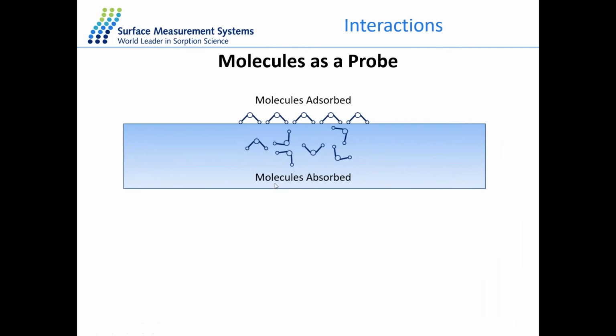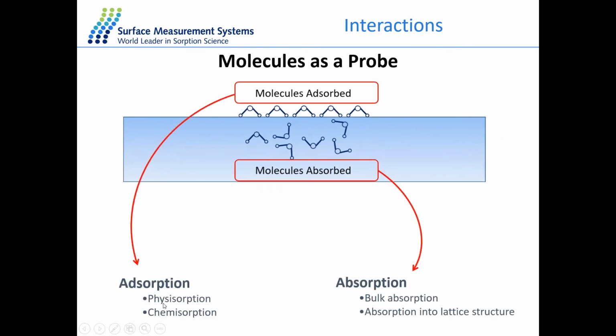In case of the molecules adsorbed on the surface, it will be either by physisorption or chemisorption. In this case, we can measure all the surface-related properties, for example, the surface area of the material, the pore size of the material, and we can also get the surface energy or heat of adsorption from a set of DVS data as well. And in terms of absorption, the probe molecule will not only be on the surface, but also penetrate the surface and go into the bulk of the material.